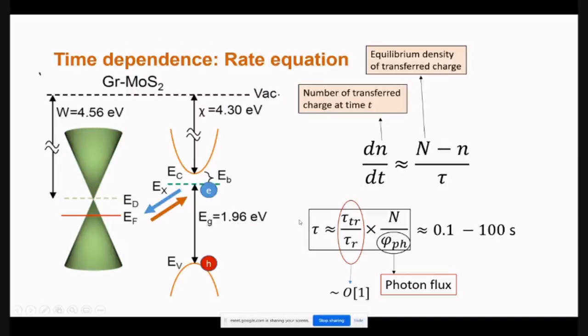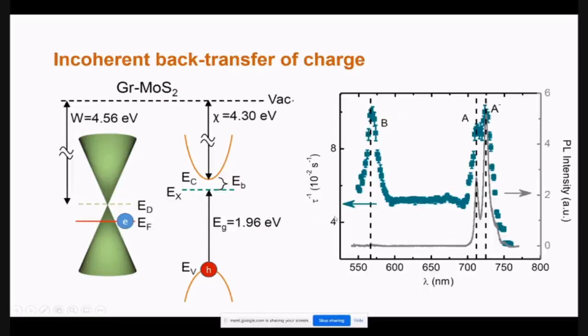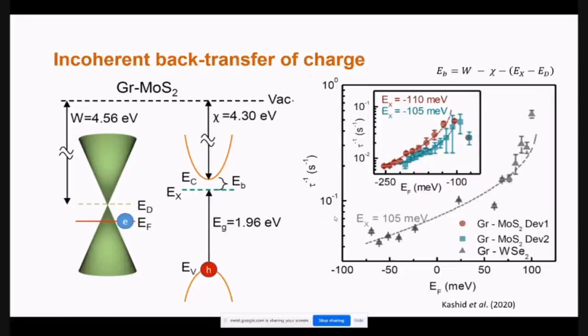Given the fact that the number of photons you apply is proportional to the power of excitation, it also shows that when the power is very low, then this time will become very large, as we see experimentally as well. Okay. Using this, actually, Tanveer could also measure the binding energies. So this is the physics of charge transfer.